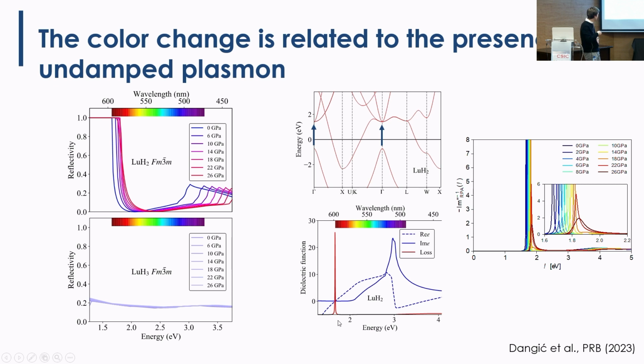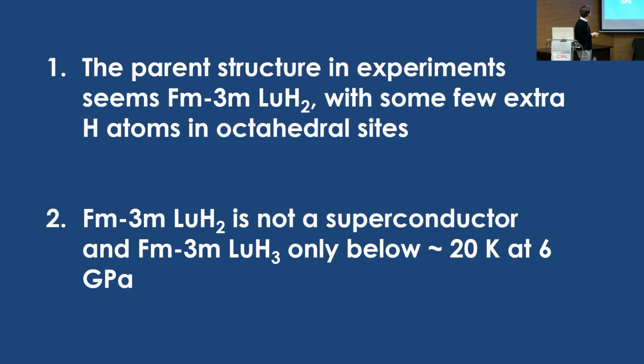So this is the real part, and the imaginary part of the dielectric function. It has a strong peak here, which is related to these transitions. And therefore, by Kramers-Kronig, this makes the real part pass through zero here, where the imaginary part is 0. So there is an undamped plasmon here in the loss function. That's why it's very sharp, and this explains the color change in this material, okay? So in conclusion, what was the conclusion? It's that lutetium H2 seems to be the parent structure here because it explains the color change observed there, okay?